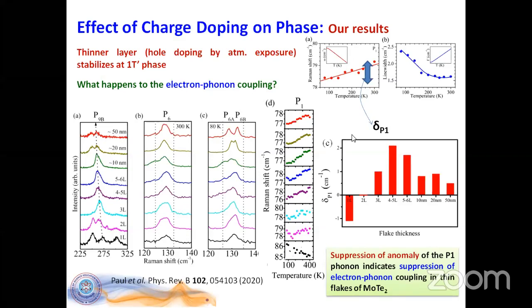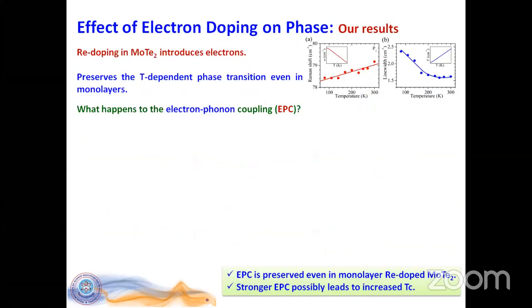If we estimate this delta, the change in the phonon frequencies with temperature, it gives us a measure of the electron-phonon coupling. We see that reasonably thick films have quite reasonable electron-phonon coupling, but in the 2-layer it gets compensated due to inherent hole doping and exposure to the atmosphere. And then in 1 layer, it gets entirely electron doped. So here it shows the loss of electron-phonon interaction in this system.